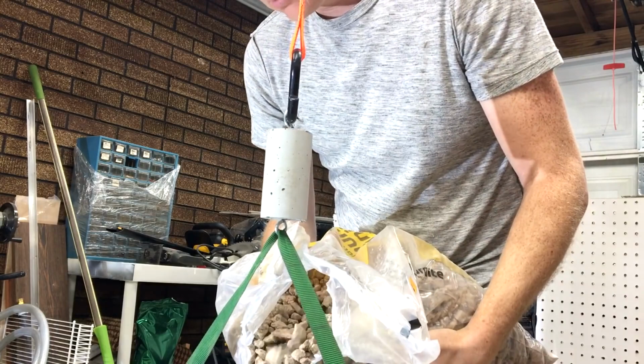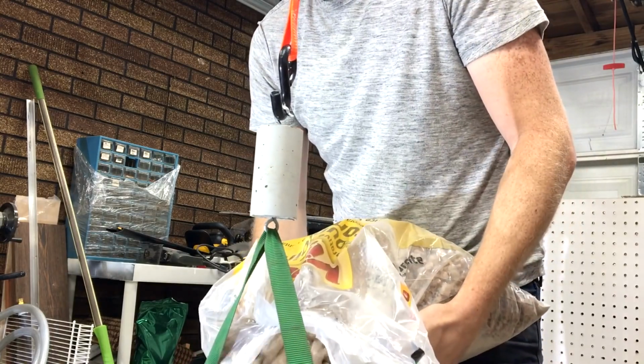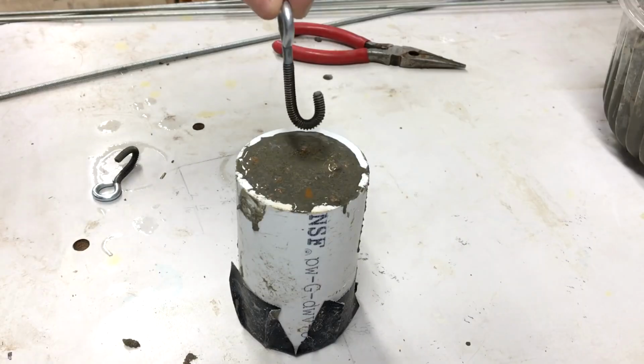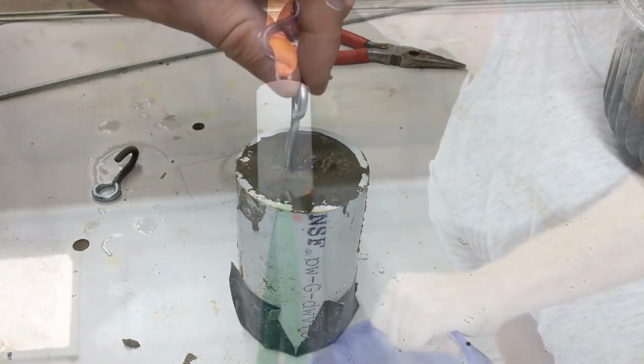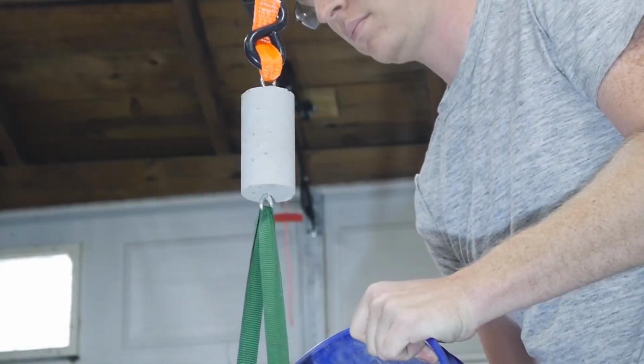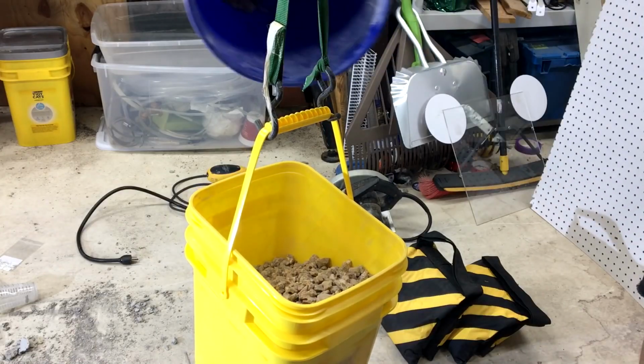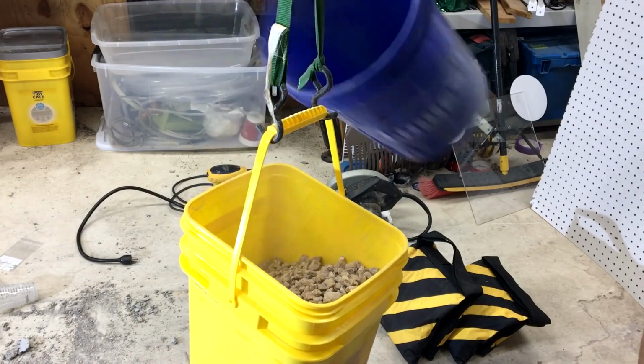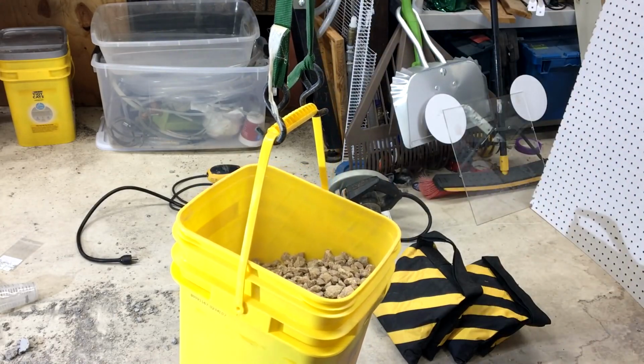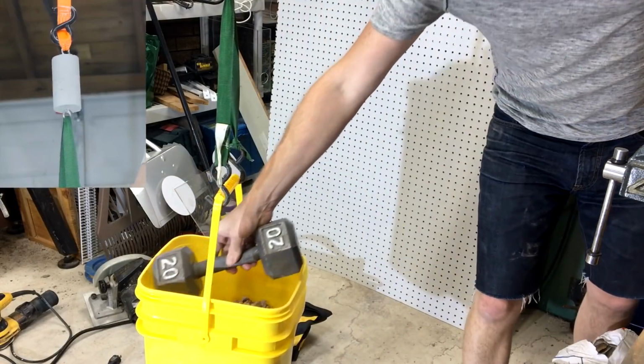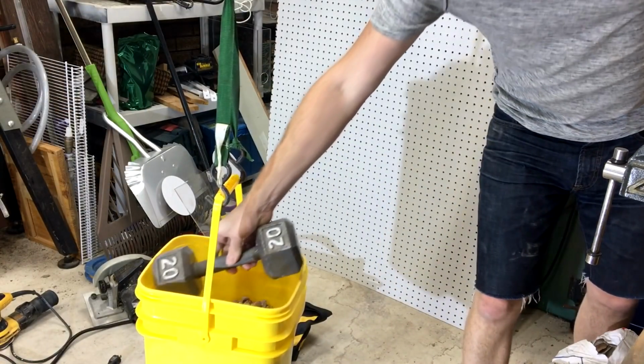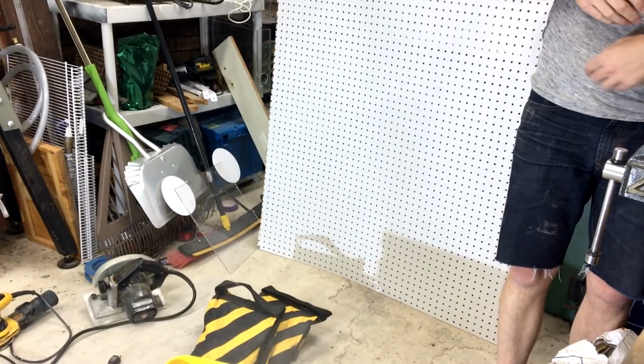The reason is my rig to test tensile strength isn't quite as sophisticated. I cast some eye bolts into the sample and now I'm hanging it from the rafters in the shop. I filled up this bucket with gravel, but it wasn't quite enough weight to fail the sample, so I added another dumbbell to push it over the edge. The weight of this bucket was only about 80 pounds, or 36 kilos. That's less than 10% of the compressive strength. All this to say, you shouldn't make a rope out of concrete.